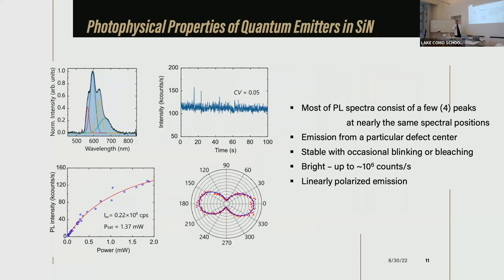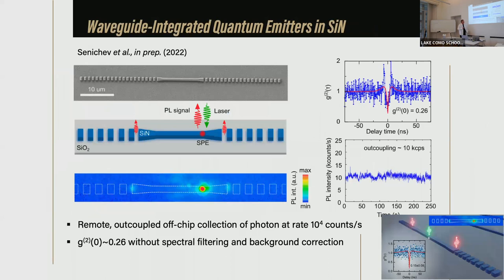It's stable, meaning this time you don't see quenching or whatever, it's stable. So the number of counts approaches 1 million counts per second. Routinely, it's always hundreds, thousands of counts per second, in many cases approaching 1 million counts per second. And they have linear polarization as expected for single photon sources. So we realized that it's indeed important and it could have a significant impact.